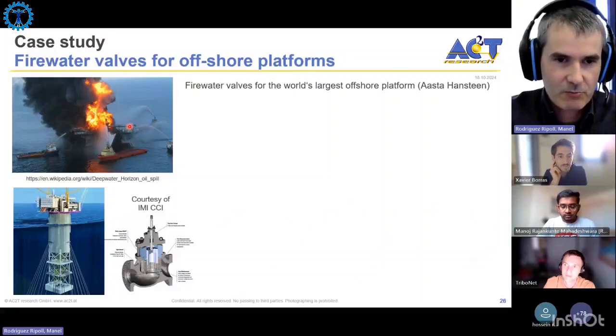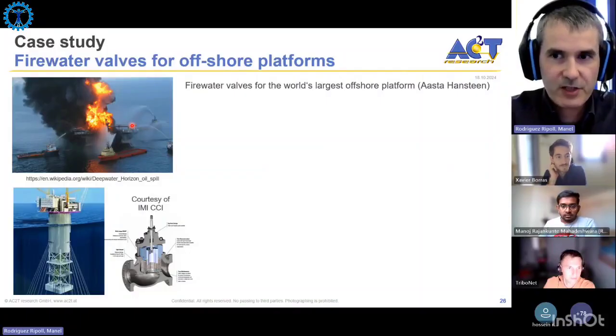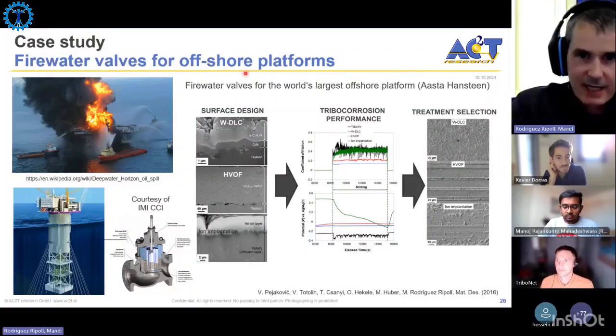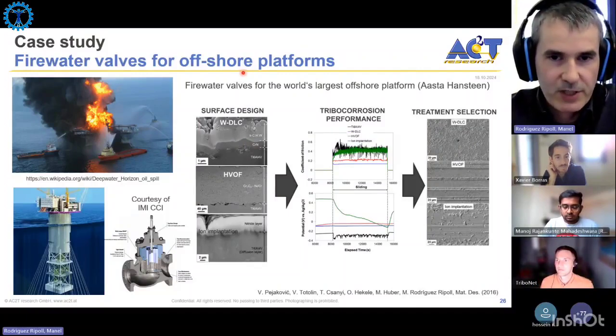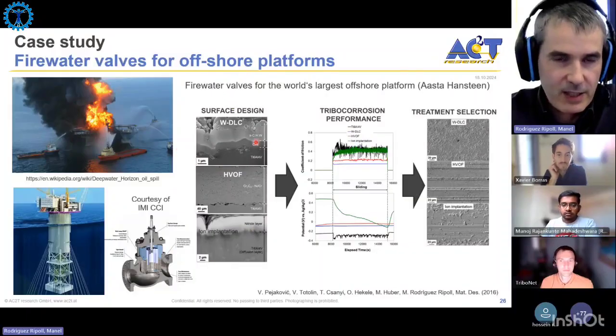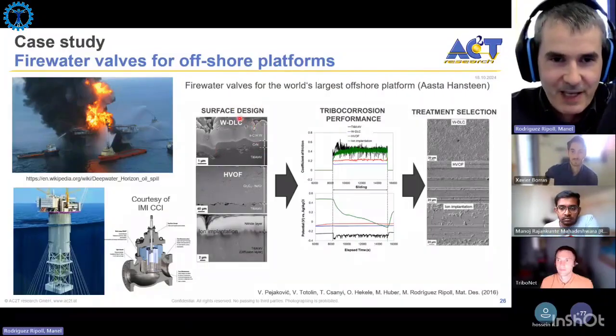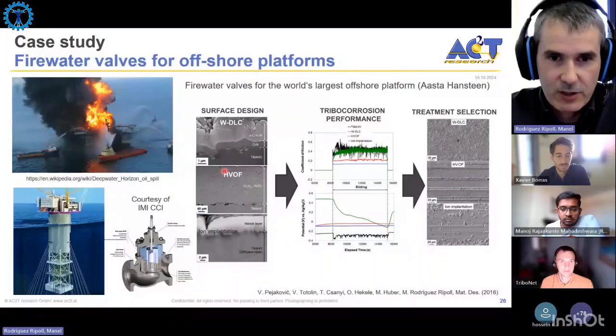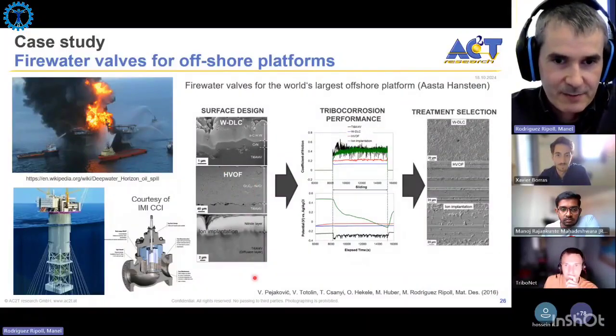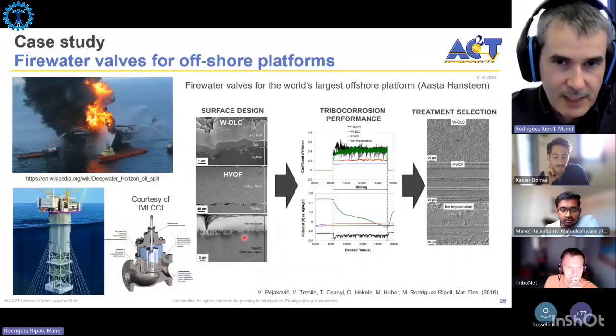They need to be operational for 10 years. Since titanium has very poor wear performance, the corrosion properties of titanium are very good, but the tribocorrosion properties are not so good. We were dealing with how to select a suitable surface treatment for these fire water valves. Here is an example of how you can use these very simple open circuit potential experiments for screening different surface treatments. We were evaluating a tungsten-doped DLC coating, a thermal spray coating deposited by high velocity oxygen fuel, and a nitride layer made by ion implantation, so by plasma nitriding.